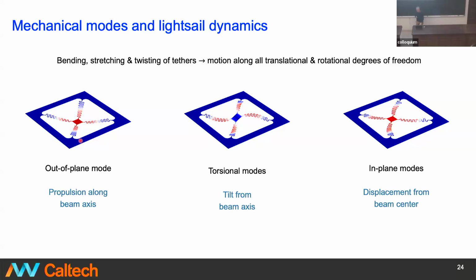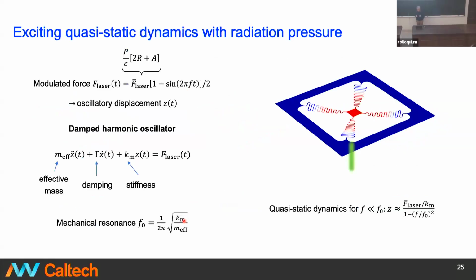We actually got to learn a number of very interesting things about the in-plane and out-of-plane modes, torsion, and translation. So if we excite well below the mechanical resonance frequency, we excite this with radiation pressure, so-called quasi-statically. We're pushing on it, applying an AC modulated signal, but it's way below the fundamental resonant frequency. This little light sail structure, which is tens of microns in size, allows us to do experiments with ordinary laboratory watt scale lasers. We don't need kilowatt or megawatt lasers in the lab, but we can study the dynamics. In this case, we have just a damped harmonic oscillator. We could easily find the resonance frequency and determine the quasi-static dynamics. So it's very similar to statically pushing on an object if you're far away from the resonant frequency. In other words, you don't see any significant phase shift.